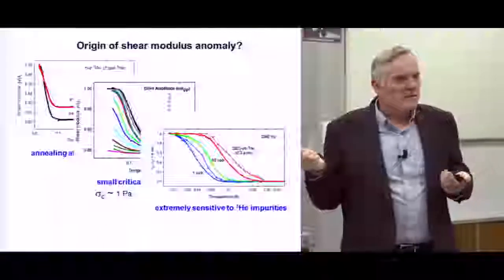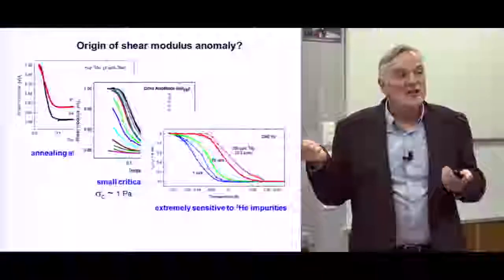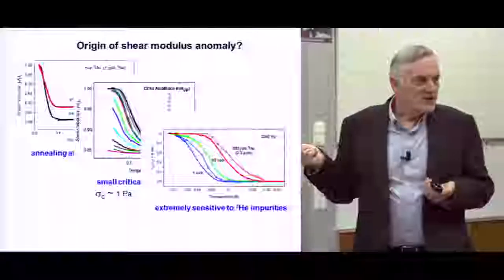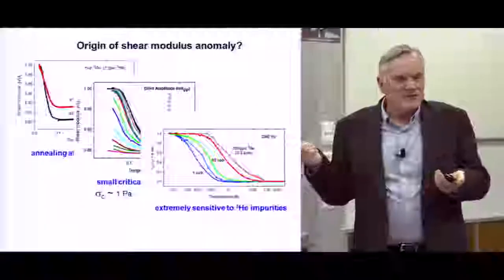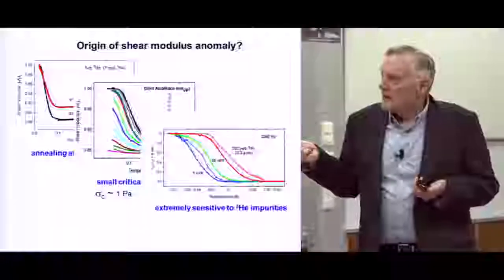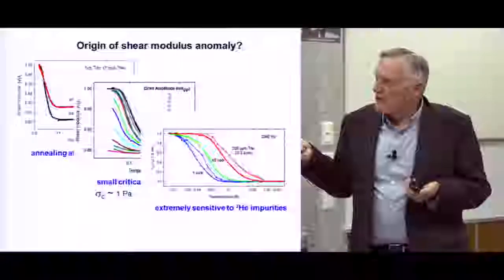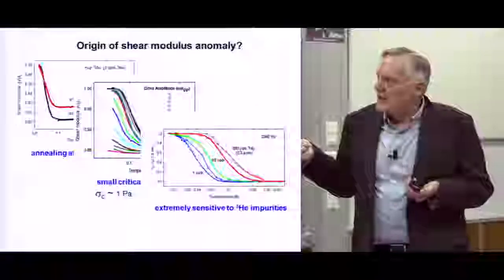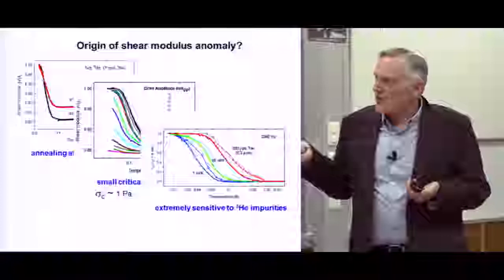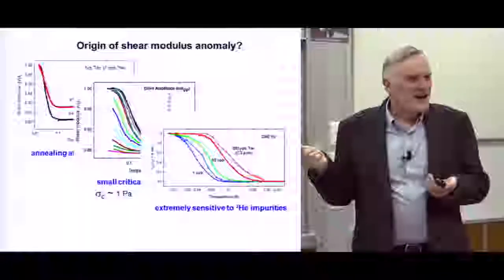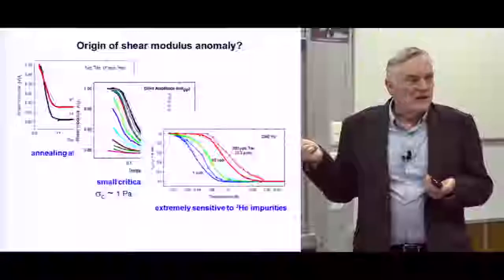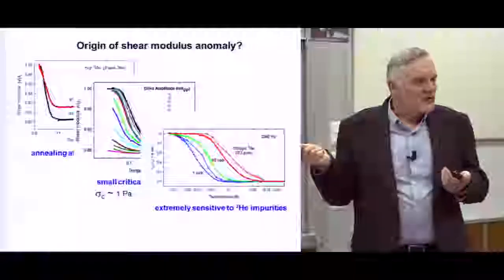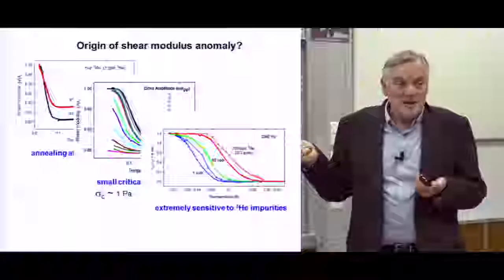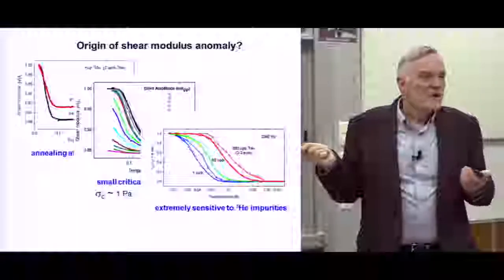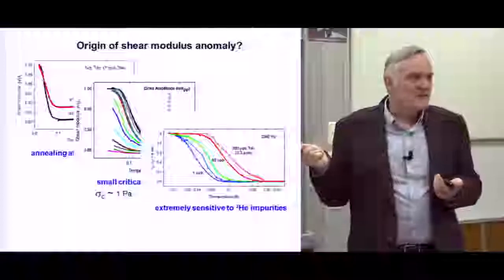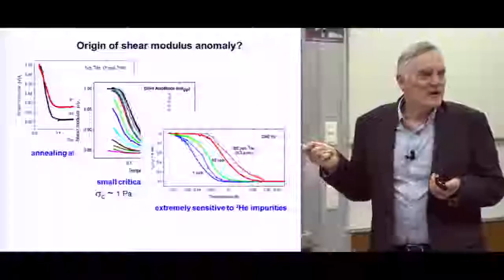So regular helium that you buy from the supplier has maybe 100 parts per billion, 10 to the minus 7 concentration of helium-3. You cool it down, there's nothing but helium-3, everything else freezes out. But going from a couple hundred parts per billion of helium-3 down to high isotopic purity, 1 part per billion, which is just getting rid of the last tiny little bit, it actually changes all the temperatures by a factor of 2. So it's incredibly sensitive, and that's not it. If I got rid of that 1 part per billion, it would keep going down. So even a part per billion is affecting the behavior of this isotopic impurity that's chemically identical to the host.